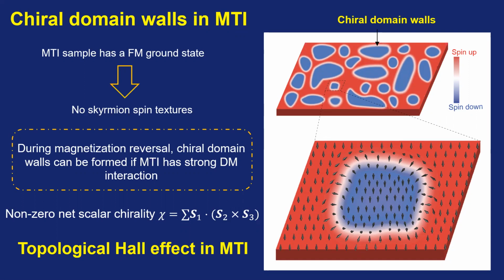So this is just a schematic for our sample. The blue color is spin down, the red color is spin up, and between the spin up and spin down in this magnetic domain regime, there is this kind of canted spin order. There is some chirality in this regime. So when the magnetic field is tuned to the QAH regime, it can show this kind of chirality in this sample. So the second image, is that a real image or also a schematic? Also a schematic. Yes.